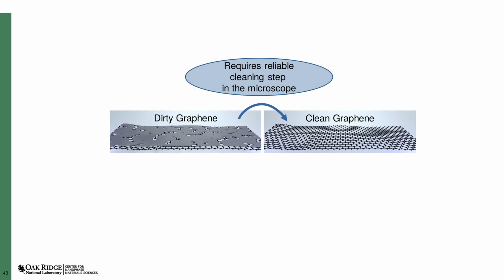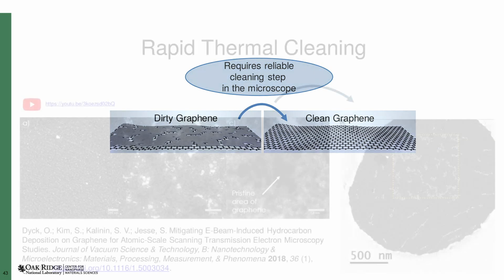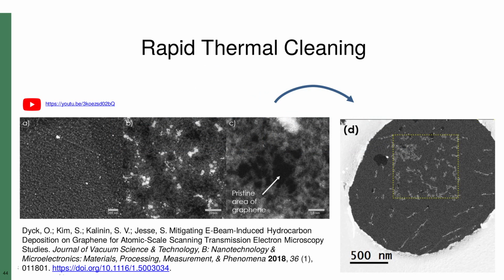Let's look at the first problem, getting the graphene clean. There are many papers detailing various methods for cleaning graphene. The reason why they are so numerous is that despite all our efforts, graphene remains dirty. In fact, graphene gets dirty in just a few minutes on exposure to air. So, having a variety of cleaning methods to fall back on is advantageous. In the publication shown here, we demonstrate an in situ cleaning technique where we rapidly heat the sample to remove the surface residue. With this technique, we can go from the level of contamination shown here to almost perfectly clean graphene. All of the uniform gray intensity is clean graphene, with a few stragglers left that show up bright in this imaging mode. This looks great, but there is slightly more going on than meets the eye.